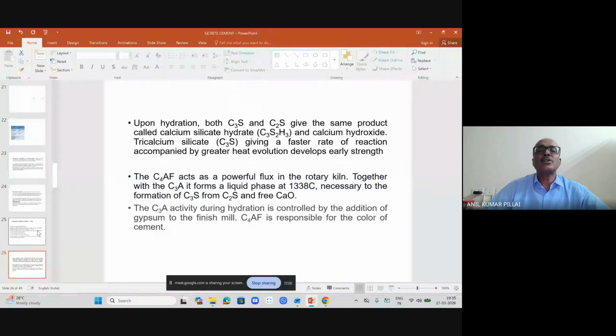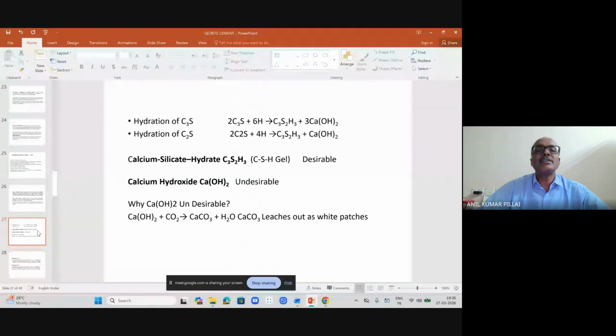So this is how the terms C3S and C2S come about; don't go by the formula. In cement chemistry, the C represents calcium oxide, S represents SiO2, that is silica, and H represents water. So the C3S, C2S, they actually form what we call the calcium silicate hydrate, and the calcium hydroxide is also generated in the process of hydration of cement with water. So that actually is very important to note, because what is desirable is the calcium silicate hydrate.